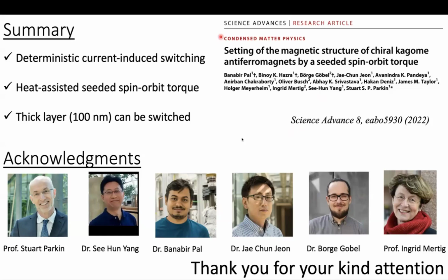I want to ask about the deposition method of your manganese tin. Is it by sputtering or MBE? Yeah, it was by sputtering. We used co-sputtering. We took one manganese target and one tin target and co-sputtered. The deposition was done at elevated temperature: we deposited at 200 and then annealed at 350 degrees, so nearly in situ in the deposition chamber.